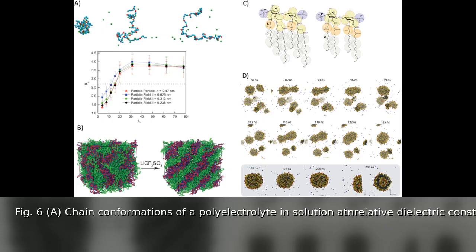Panel B highlights phase separation in block copolymers induced by salt, modeled with Martini-like mapping within HPF models. Furthermore, CG models of charged surfactants like SDS and lipid bilayers including palmitoyl oleoyl phosphatidylglycerol have been proposed and validated, enabling explanations of micellar morphologies at varying concentrations. Panel D focuses on biological variants of lipid A, showing HPF-MD predicts lamellar and micellar phases, along with spontaneous vesiculation from fusion of micellar aggregates. These applications underscore the adaptability of HPF-MD to complex charged polymer and biological systems.